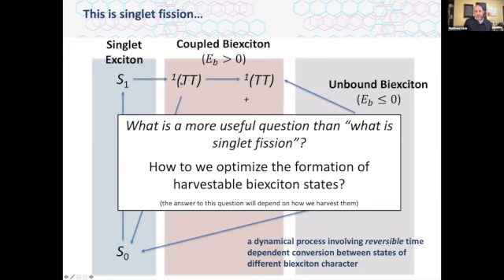You cannot directly form the quintet. No one believes you can directly form the quintet, I think, because of, again, spin angular momentum considerations. There's no way to get from the singlet to the quintet, but there's ways to get from the net singlet to the net quintet via various mixing processes. So one way to do it is to bring the singlet and quintet close together. That's true when we have these diffusive processes where, as we pull them apart, the exchange coupling gets weak, and then they start to mix, because again, the spin is no longer a good quantum number. You can also have spin orbit coupling that will mix them. There's also orientational effects that will start to mix them. So there's all sorts of ways to get from 1TT to the rest of them, but not a good way to get from S1 to quintet directly. I don't think there's anyone who would argue with that, although maybe there is.